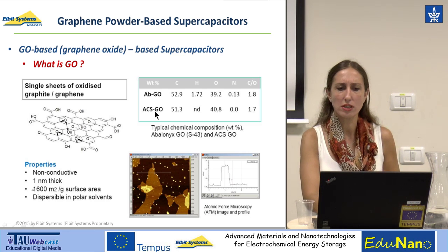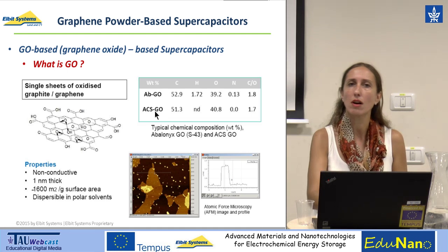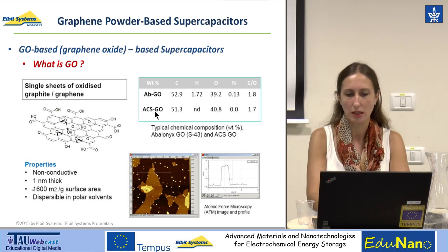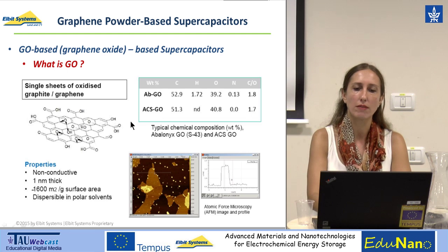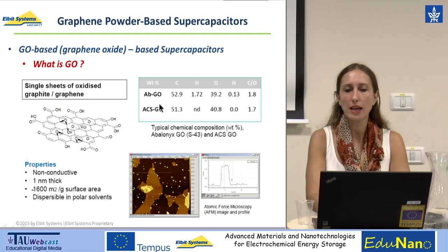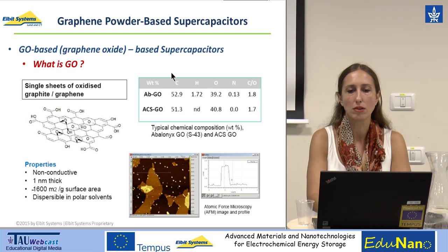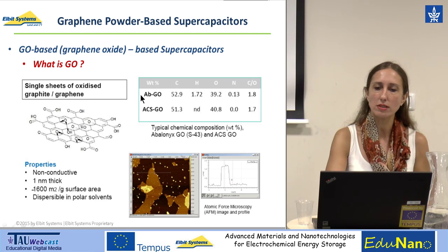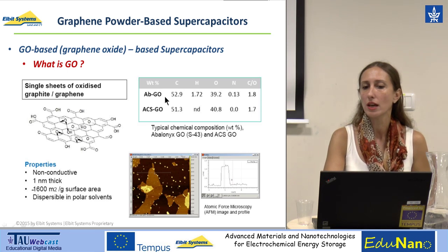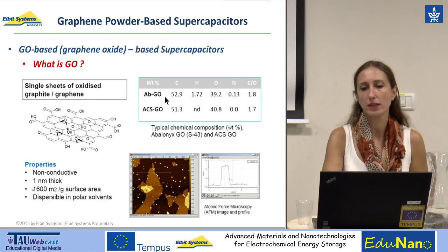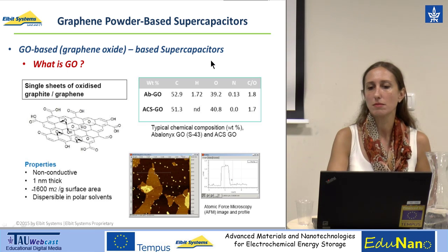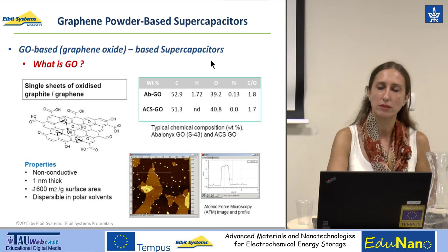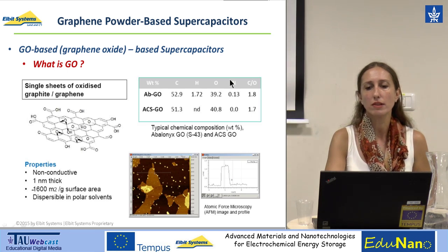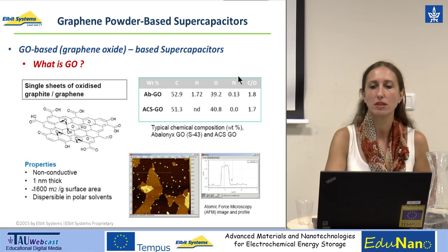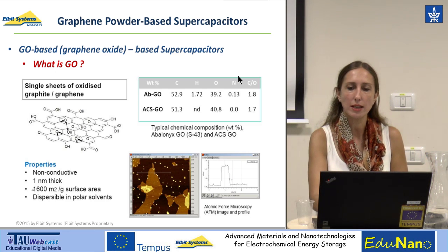What I'm taking here to show you is the Abalonyx graphene oxide. Abalonyx is a commercial company that produces graphene oxide, and they have two samples. They have the GO and the ACS-GO. What is the difference? Of course, the chemical composition. So in the Abalonyx GO, we have a carbon content of approximately 53 weight percent, and the ratio between carbon and oxygen is 1.8, with impurities of hydrogen and nitrogen at 1.7 weight percent and 0.13 weight percent respectively.